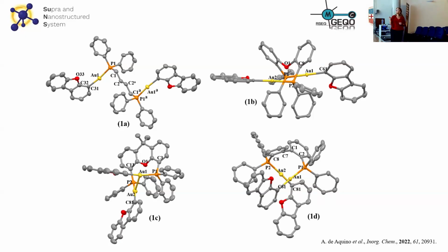and we can observe clear differences. The most flexible diphosphine is this one, where the chromophores are in a head-to-tail conformation, so they are not looking at each other. There is no possibility of establishing aurophilic interactions, at least in an intramolecular way. But if we modify the diphosphine a little bit, closing it with this ring, we can observe that these two arms are closer to each other, although not enough to establish aurophilic contacts.